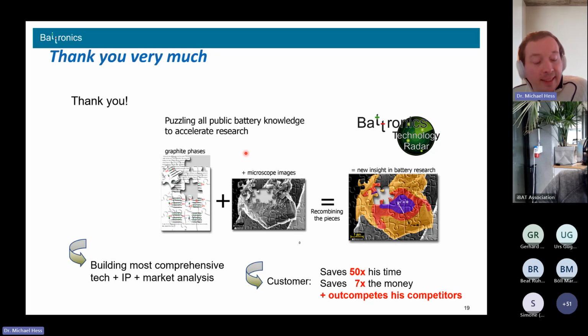Exactly. So the nice thing is, I did not deep dive into that due to the time that we had for the presentation. But usually it's not like when you test the first battery, the second one with the same chemistry will be totally off. So yes, you will have similarities between different similar LFP cells. You will learn that you may not need 9 SOC data points, but only 3 or 4, and only 3 or 4 different temperature profiles, because there are scaling laws behind, usually based on standard physics that we know, like Arrhenius for temperature dependencies, and SOC dependence is usually graphite based and so on. So yes, there exist repetitive patterns.